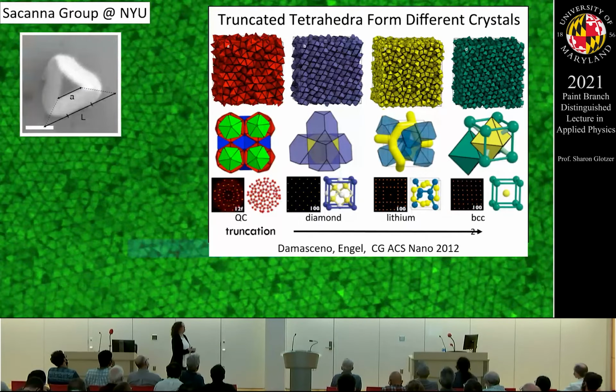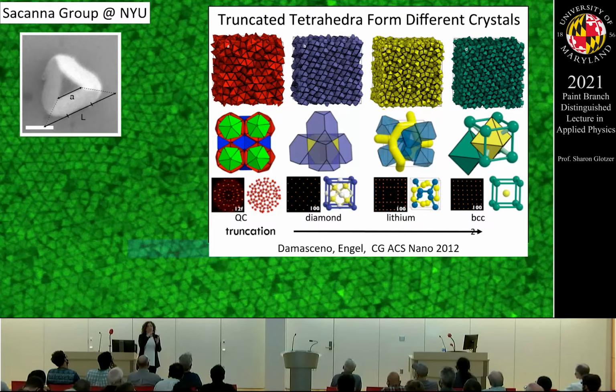If you change the shape, you change the crystal structure. If we start truncating the tips of these tetrahedra, then at some point, instead of the quasicrystal, you can get diamond. If you keep truncating more, you get a phase that's isostructural to a high-pressure lithium phase, which has 16 particles in the unit cell. And if you truncate the corners of a tetrahedron enough, eventually you get a perfect octahedron, and that self-assembles into a body-centered cubic crystal.